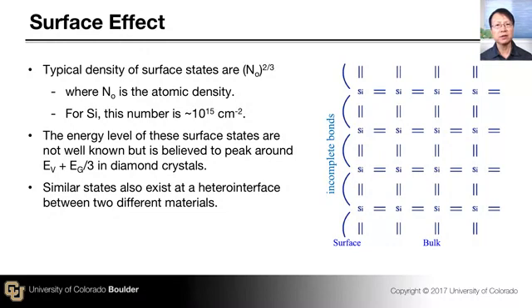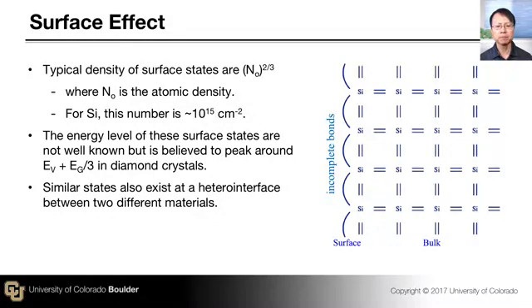There are many varieties of defect states possible depending on the exact termination of the surface. In general, the density of surface states is known to be proportional to roughly the two-thirds power of the atomic density. For silicon, this number is about 10 to the 15th per square centimeter, which is a pretty substantial number. The energy levels are spread over a range, peaking around one-third of the band gap from the valence band in silicon and other diamond-structure semiconductors.